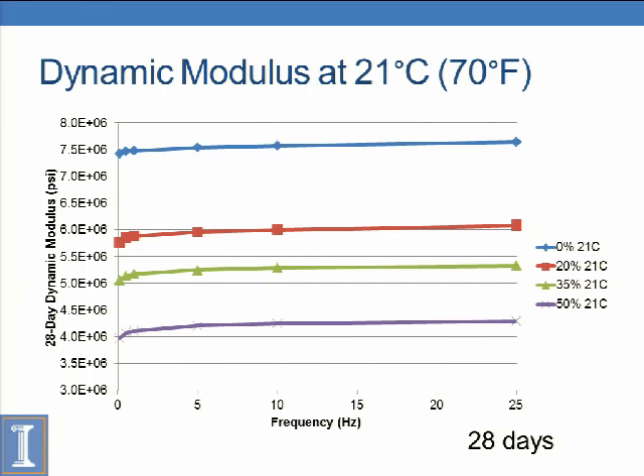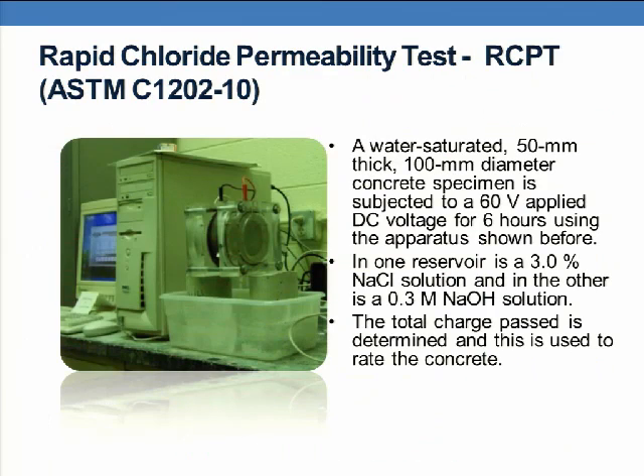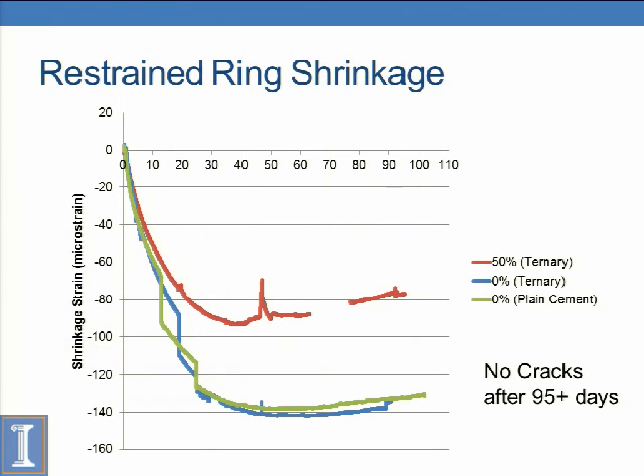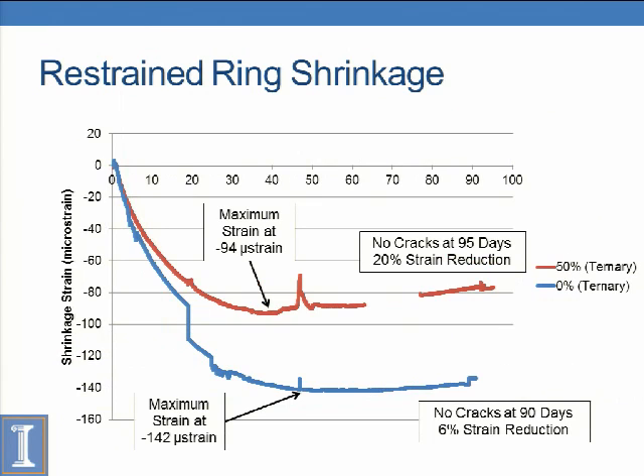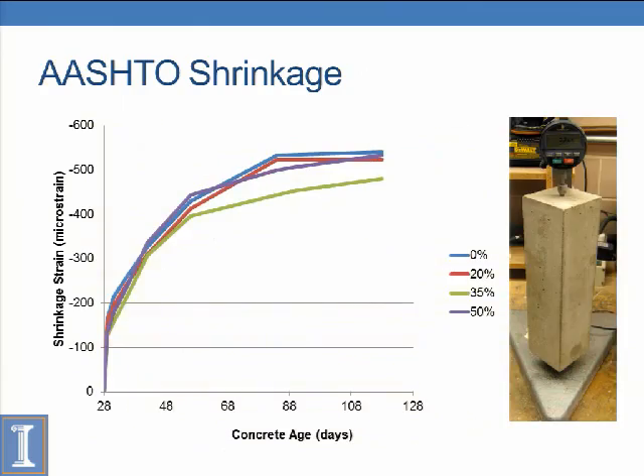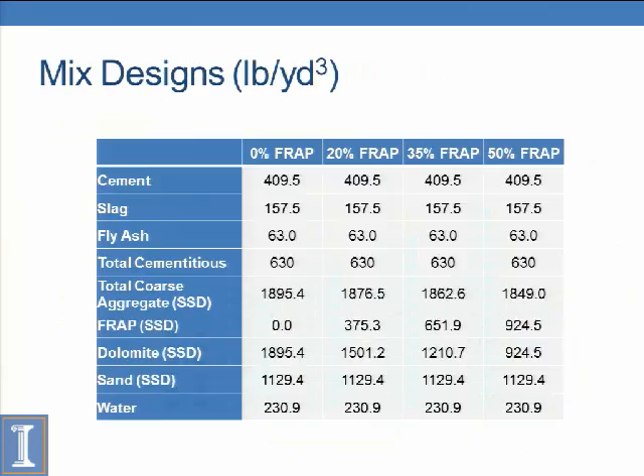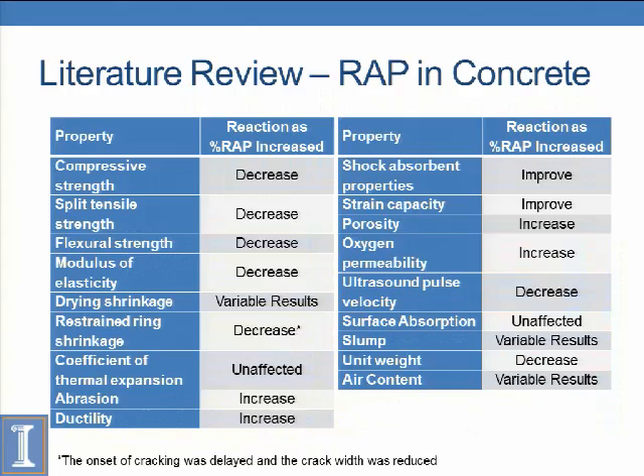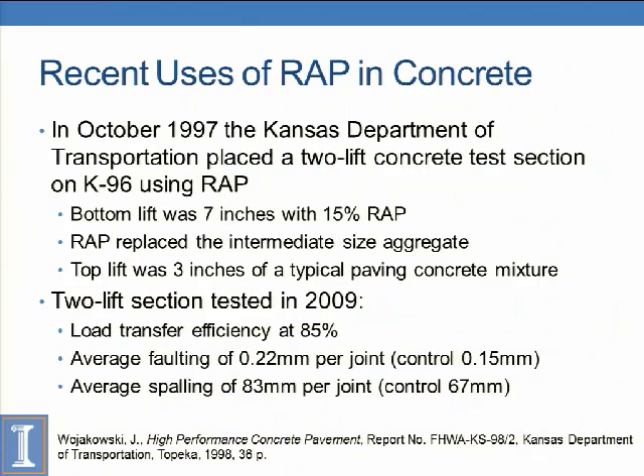You mentioned the slab deflection faulting problem in one of your cases, and it was a little bit higher. Yeah, that was the Kansas DOT's study. It was a very small faulting, despite the concrete being over 10 years old. It was a pretty low faulting. Here it is. Yeah, the faulting was 0.22 millimeters per joint versus the control at 0.15.